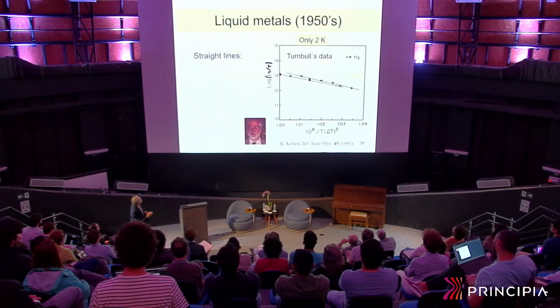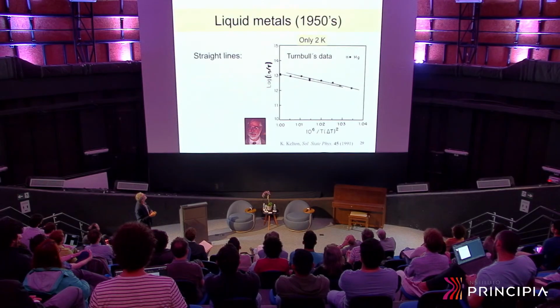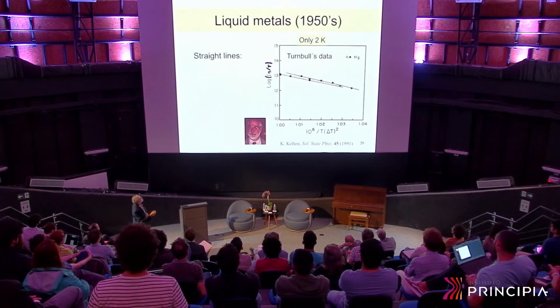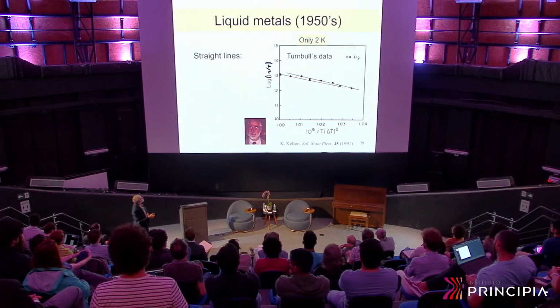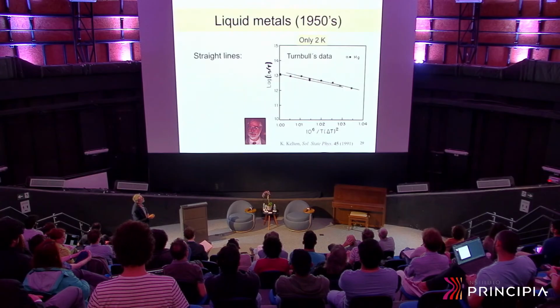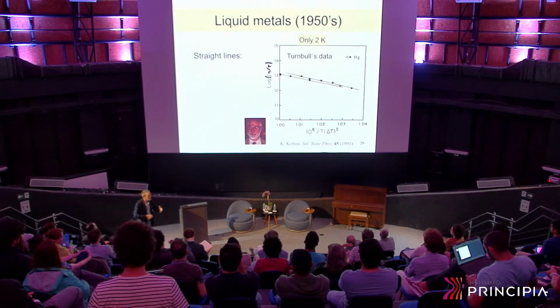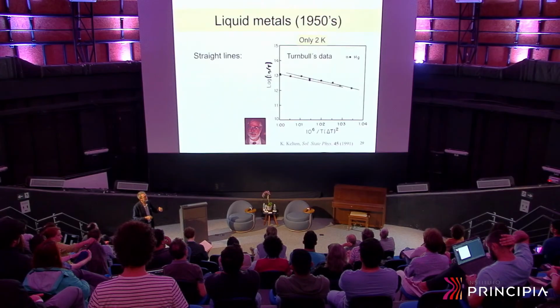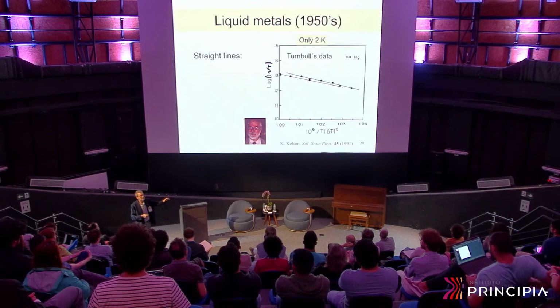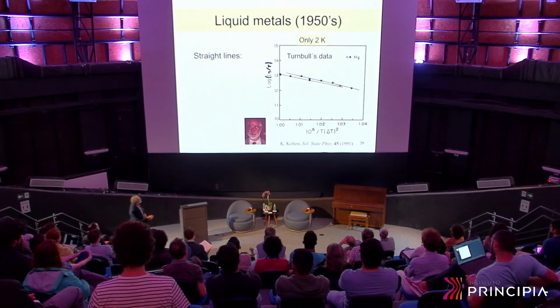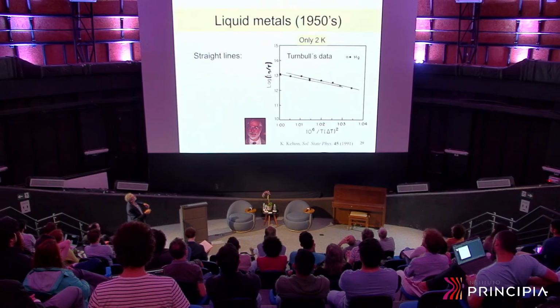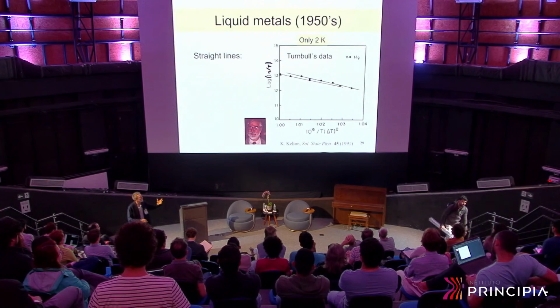Testing the theory. Okay, the first guys to test, more or less in the early 50s, were able to measure nucleation rates in liquid mercury. Mercury is a metal, which is liquid at room temperature. You can cool it down and measure nucleation rates. See, two sets of experiments here. This is just a linearized plot of that equation. It's the log of nucleation rates times the viscosity divided by T versus 1 over T delta T squared. It's just a linearized form of the equation.